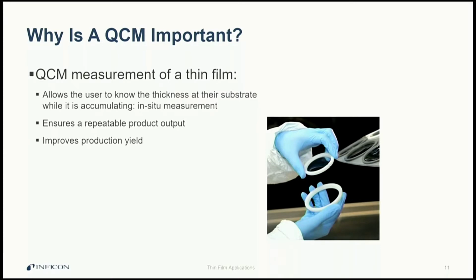By using a QCM, you are able to ensure that the thin film will be the same thickness for all substrates used in production. This improves the production yield and the overall quality of your coatings compared to measuring thickness after the deposition has taken place, which would be known as an ex situ measurement.